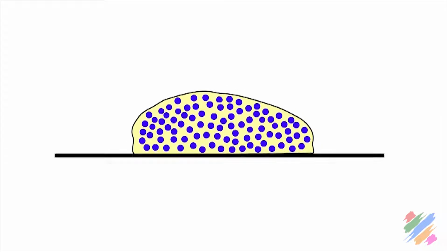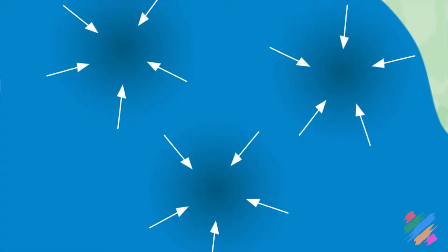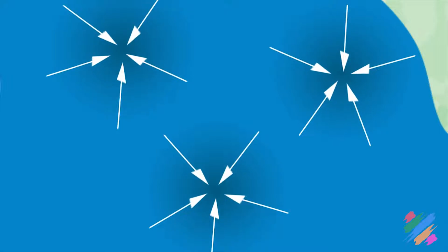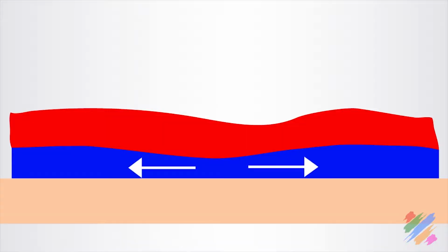We have seen that during the polymerization our oil colors will shrink. And we have also seen that it's not a process that starts and proceeds uniformly. That we will have areas where it starts earlier and areas where it starts later. In few words, while the polymerization goes on, our paints will shrink in the direction of those areas. So, to make it simple, the bottom layer will pull the top layer, which at a certain point will break, and we will see many cracks appearing on our painting.